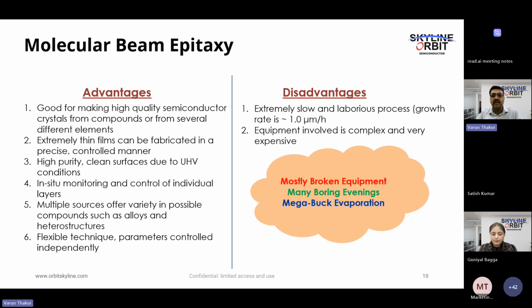Disadvantages: it is a very slow and laborious process. Because we are trying to make atomically sharp interfaces and single layer by layer growth, of course it is very slow to grow. So it's basically 1 micron an hour is the kind of standard growth rate. It is lower or higher based on your specific conditions. That is why recipes are very important here. Like if you want to grow a 5 micron or 10 micron thick layer, you need to let it go for a few hours. So that is why recipes are important here.